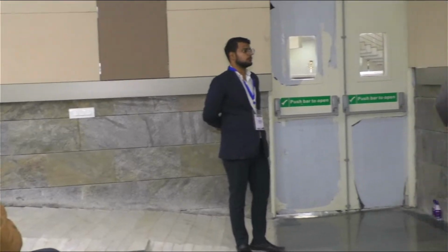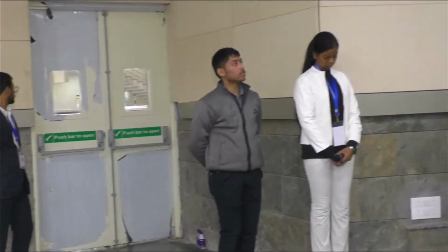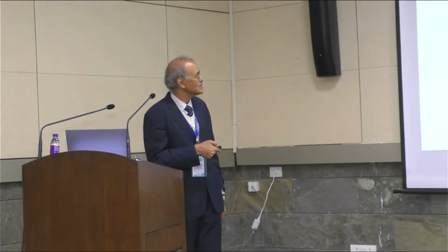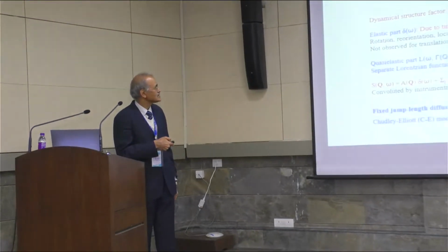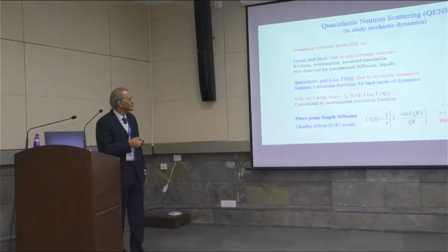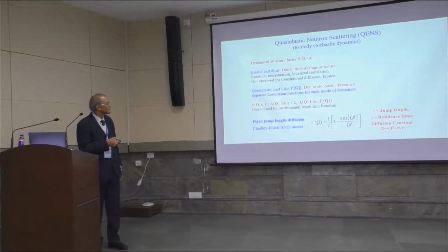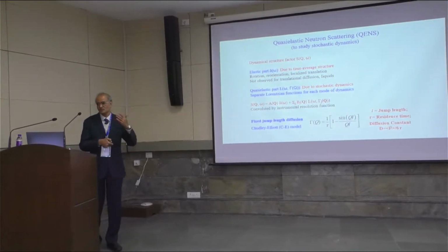Okay, this is h cross q will be the momentum and h cross omega will be the energy. Here again there is a certain elastic part which is due to the time average structure, and there is a quasi-elastic part. So the broadening part, we fit it with a Lorentzian function. If you fit it with a Lorentzian function, then this width of the Lorentzian can be related to the different kinds of modes of the dynamics.